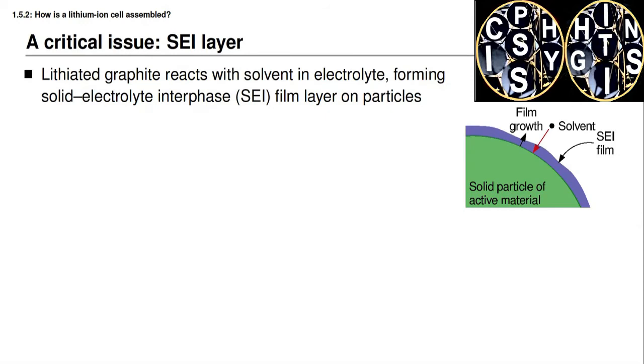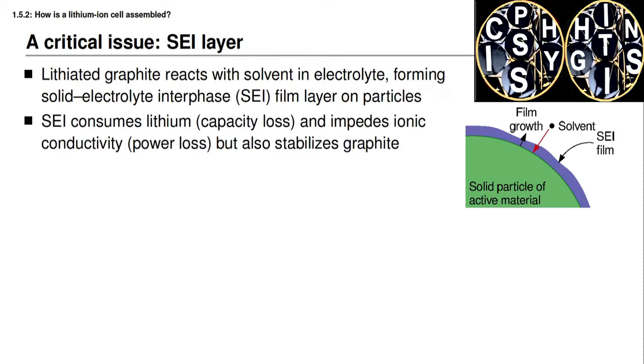Before we discuss this charging process, it's important to talk a little bit about something that's known as the solid electrolyte interface layer in a lithium-ion battery cell, otherwise known as SEI. It turns out that when lithium intercalates into graphite in the negative electrode, the lithiated graphite reacts with solvents in the electrolyte and forms this SEI layer, the solid electrolyte interface layer, which is a film coating the particles of the negative electrode. This process of SEI formation and growth consumes lithium, so it results in capacity that's lost.